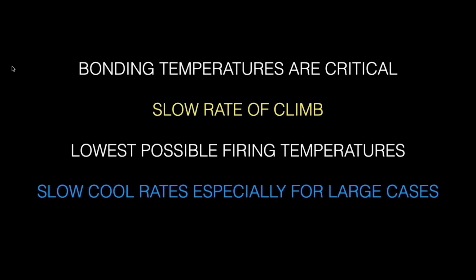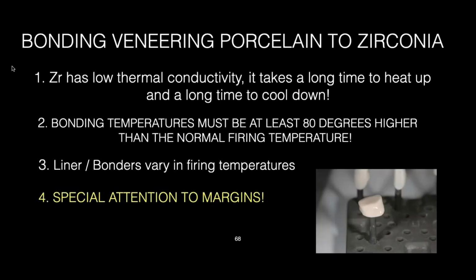So the bonding temperature is critical. You need to get a little bit higher, go at a slow rate of climb, lowest possible firing temperature till you see glass develop, which is about 800 in the Lumex material. It's around 910 on the VM9. And slow cool rates, especially for large cases. We already talked about that.